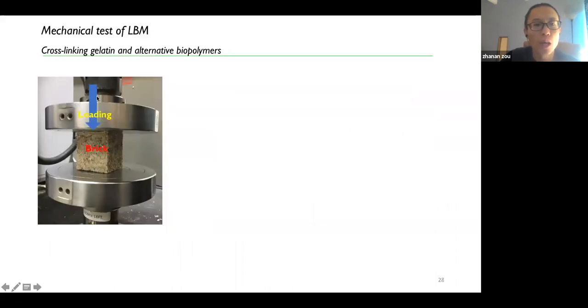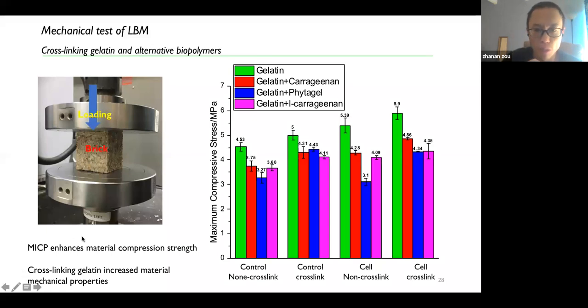Okay, so we carried out a mechanical test of the brick made with living building material. As you can see here, there's a brick sandwiched in between two metal plates. The brick is made of living building material, and the two plates are from a loading machine, and they compress the brick until it fails. At the same time, the load is recorded, and we can get the maximum loading. In one word, the higher the maximum load, the better the mechanical property is.